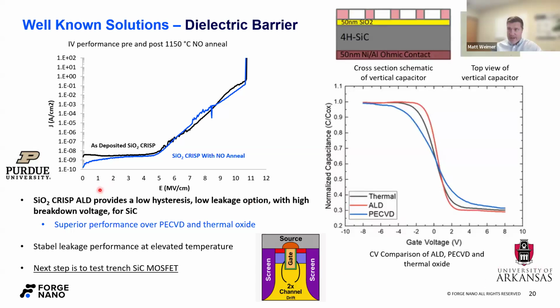The first thing I want to talk about on the left here is leakage and breakdown. I'm comparing the as deposited crisp film with the same film after a nitric oxide anneal at 1150. The first thing that jumps out is that the leakage does decrease a little bit, but it's already pretty low, right? At 3 megavolt per centimeter, that's a pretty good leakage. The second thing is that the breakdown occurs at roughly the same spot, which is above 10 megavolt per centimeter.